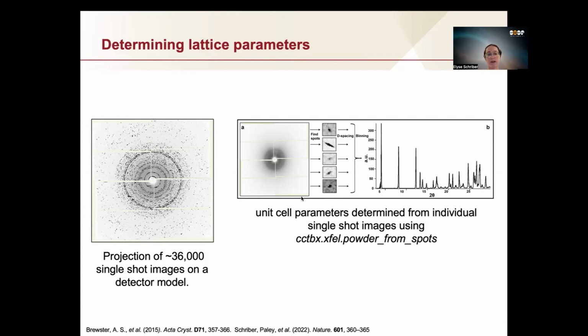So what we did is we designed a way to utilize tools that we already have at our disposal by being able to use an algorithm called Spot Finder, which we already used to find the spots in one of these single shot images. And then we can identify the d-spacing, or the actual positioning of that spot in real space, using the detector model that we already have.